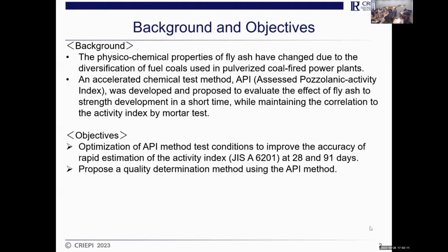And next, we need to have some rapid estimation method to obtain the properties, especially for the strength development of the fly ash. Now we apply the mortar test, then it takes about 1 and 3 months to obtain the result. So we need to shorten the testing period. And the objectives of this research I show you today is firstly optimization of API method test conditions to improve the accuracy of rapid estimation of activity index. Activity index is derived from the mortar test. And secondly, a proposal of a quality determination method using the API method. It's a goal of the Japan Industrial Standard.